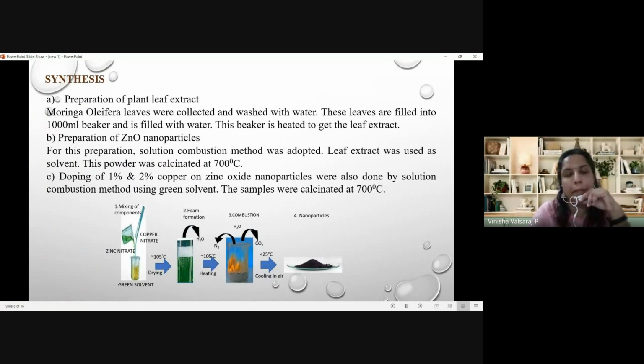Coming to our work, first of all, the synthesis part. First, the green solvent preparation, that is the plant leaf extract. For the plant leaf extract, we used Moringa oleifera leaves. The second step is the ZnO nanoparticle preparation. The solution combustion method is adopted here, and the powder is calcined at 700 degrees Celsius.